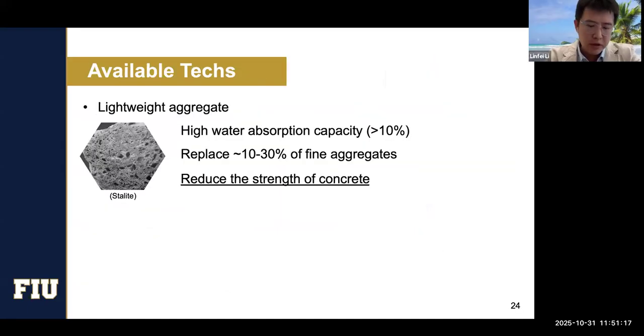A little bit of information on some of the available technology. I think the first one is lightweight aggregates. Lightweight aggregates have been promoted very well in the past years because this material is relatively cheap, and you can just use it to replace some of the fine aggregates. As you can see from the photo, it's relatively porous, so it can hold a lot of water. What you need to do is just pre-soak the lightweight aggregates.